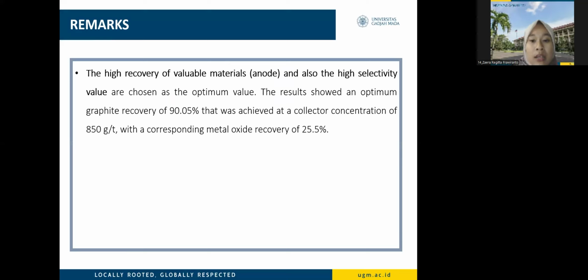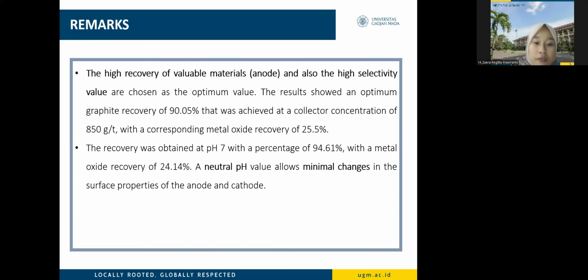So the conclusion from this research is that the high recovery of valuable material and also the high selectivity value are chosen as the optimum value. The results show an optimum graphite recovery of 90% that was achieved at a collector concentration of 850 with a corresponding metal oxide recovery of 25%. The best recovery was obtained at pH 7 with a percentage of 94% with a metal oxide recovery of 24%.